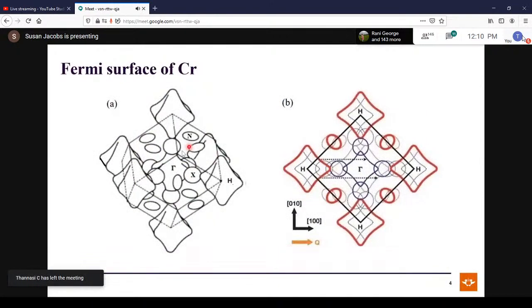Okay. So on the left, we have the 3-dimensional representation of the Fermi surface of paramagnetic chromium in reciprocal space. The solid and dotted lines represent the boundaries of the first Brillouin zone. We have electron octahedra or electron jack and hole octahedra, which are centered at gamma and H points in momentum space or reciprocal space. We also have other features on this Fermi surface, like electron knobs and hole ellipsoids, but these do not partake in the spin density wave formation. On the right, we have the cross-section of the Fermi surface in the 100 plane.